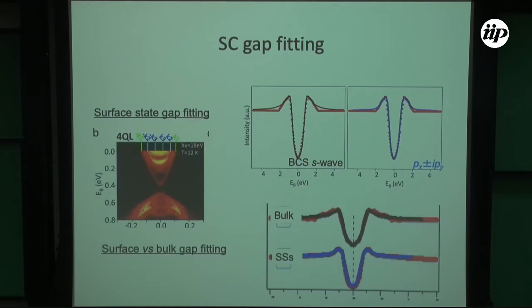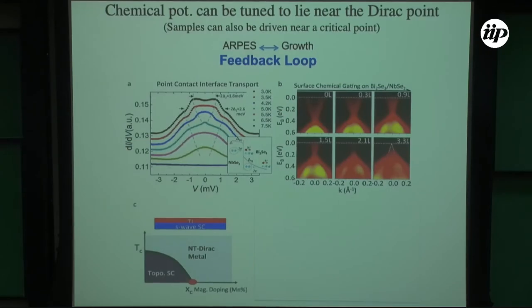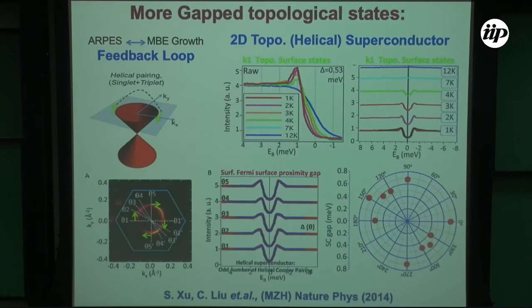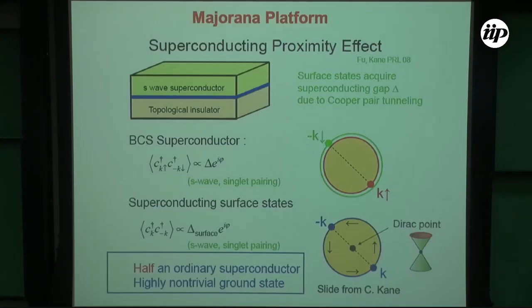But based on that, I would not conclude that I'm seeing some p plus ip. This is to answer your question about how much we learn by fitting. It looks a little better, but who knows? So what is then our claim that it's topological superconductivity? The claim goes back to here. It's a very simple proposal, Fu-Kane's. All you have to make sure is that on the surface or interface, you have a Dirac cone, and it's superconducting. That guarantees it, since with ARPES we can count all the degrees of freedom.